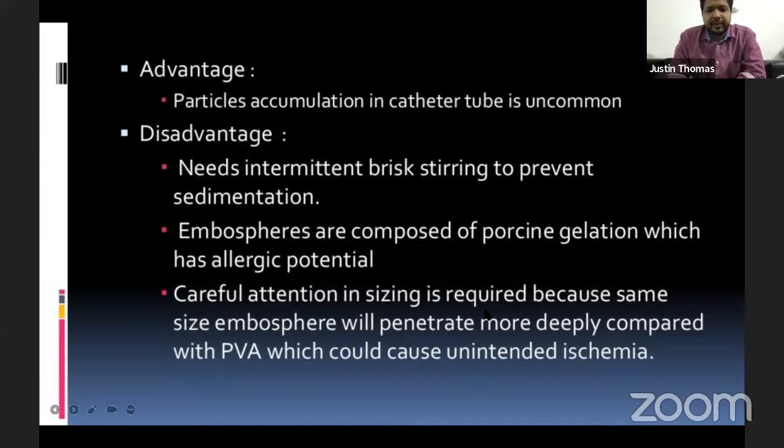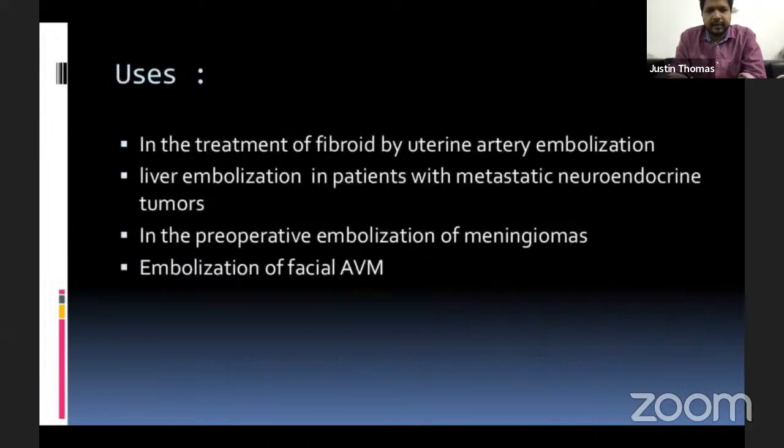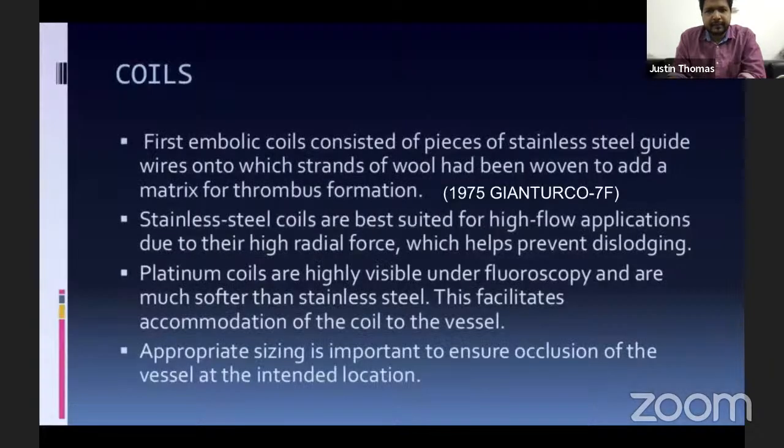And since this is made up of porcine gelatin, there is a chance of allergic reaction. And there should be adequate sizing, since the same size particles can cause deeper penetration compared to PVA. So we have seen it is used for uterine artery embolization, liver embolization, especially in tumors, and it can be used in meningiomas and also in facial AVMs.